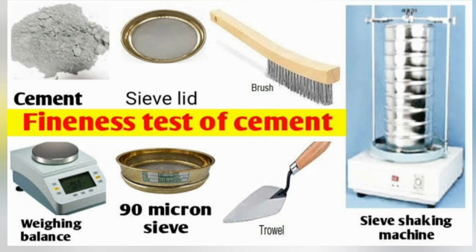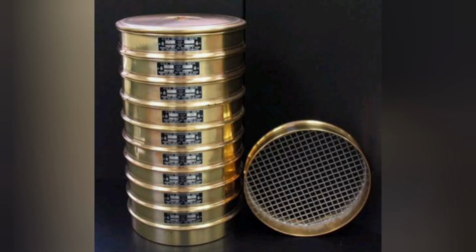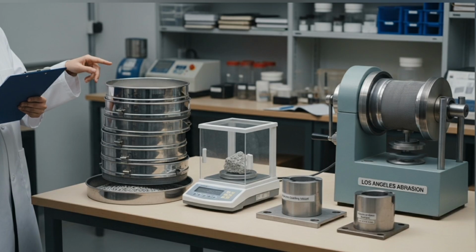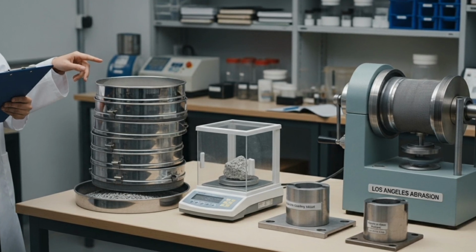In the sieve test, we shake a 100-gram sample of cement on a 90-micron IS sieve for 15 minutes. The weight of the residue left on the sieve should not exceed 10% for OPC. A higher residue means coarser particles, which will lead to slower strength development. Blaine's method is more sophisticated, measuring the specific surface area in square centimeters per gram by observing the flow of air through a compacted cement bed.